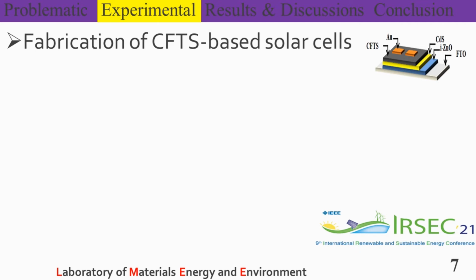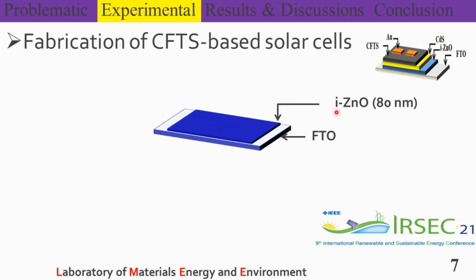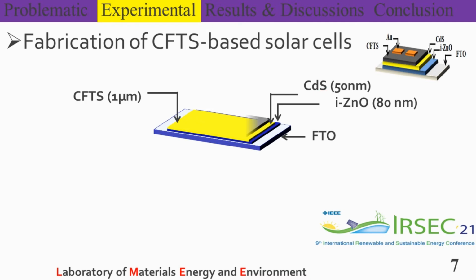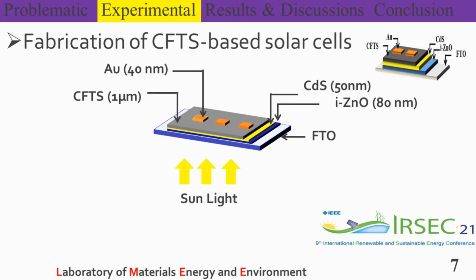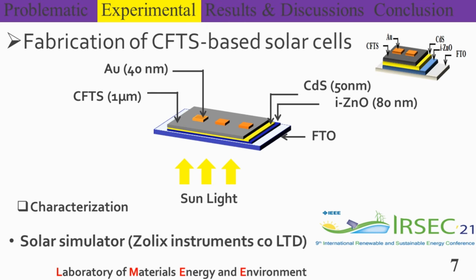The structure of the device is as follows. Firstly, 80 nanometers thick intrinsic zinc oxide thin film has been deposited by sol-gel method on the cleaned fluorine tin oxide substrate. Then 50 nanometers thick cadmium sulfide thin film was deposited by sol-gel method. After that, the copper iron tin sulfide thin film was deposited on top of the cadmium sulfide thin film. Finally, an opaque contact of gold was deposited on the surface of the copper iron tin sulfide thin film by sputter coater. The fabricated solar cell has been characterized by solar simulator.